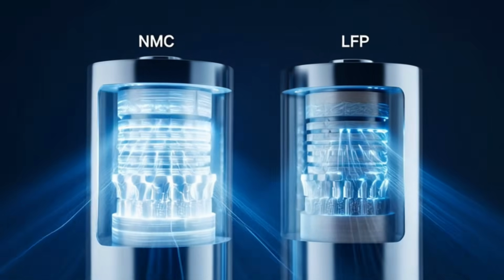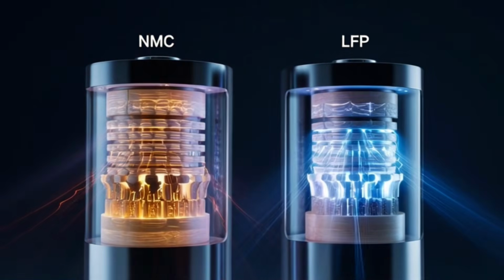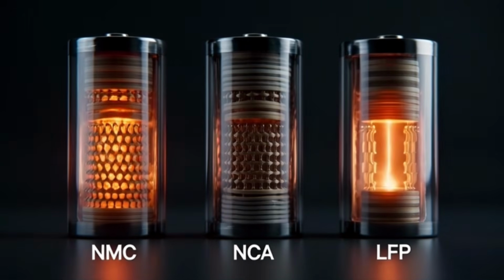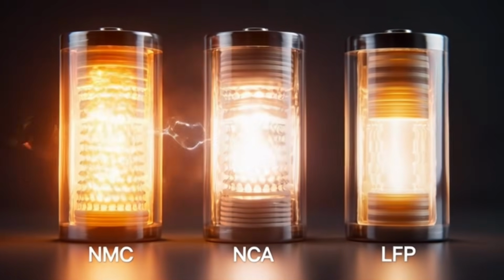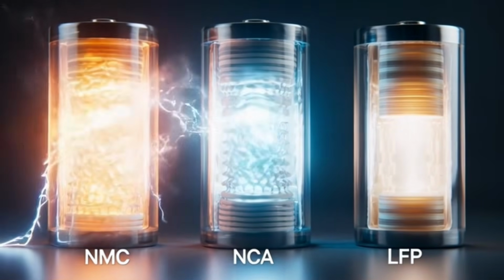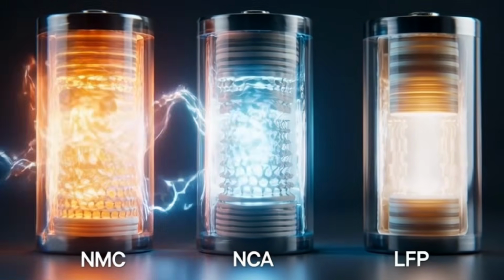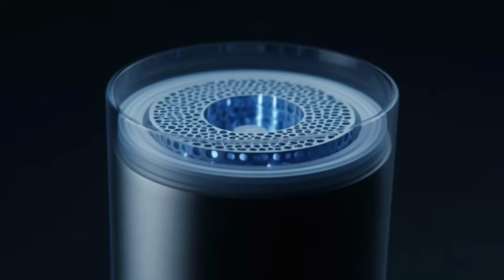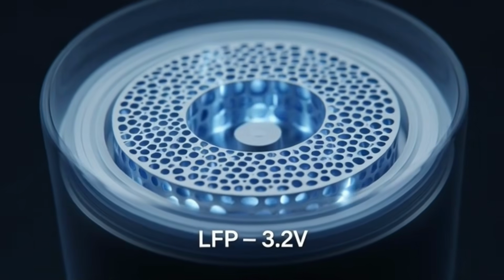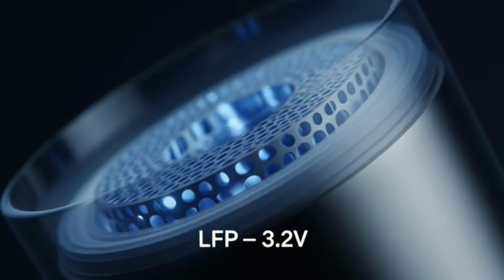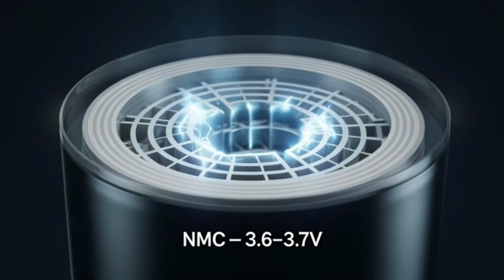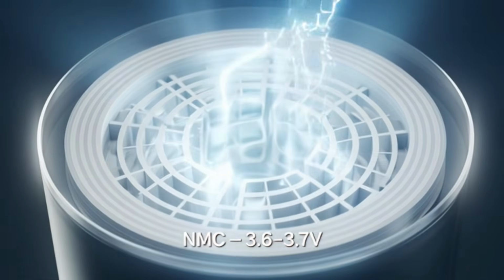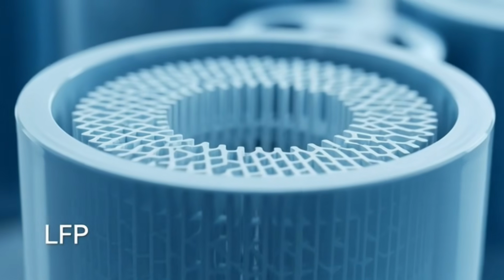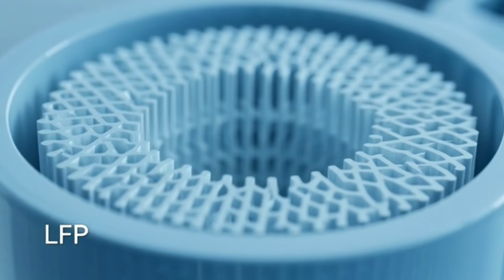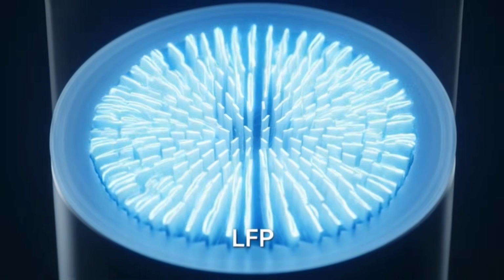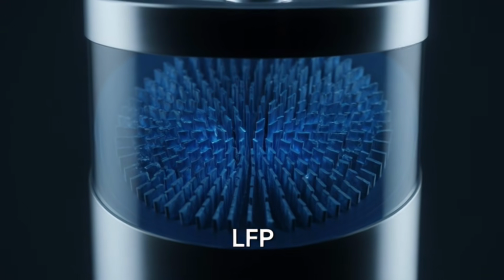NMC batteries operate at a higher voltage per cell than LFP. So every single time an NMC or NCA battery gets charged to 100%, it's experiencing more electrochemical stress than an LFP battery doing the same thing. LFP operates at a lower nominal voltage, around 3.2 volts per cell, compared to about 3.6 to 3.7 volts for NMC. That lower voltage means less stress on the materials every single cycle. Less stress, accumulated over thousands of cycles, adds up to dramatically less degradation.